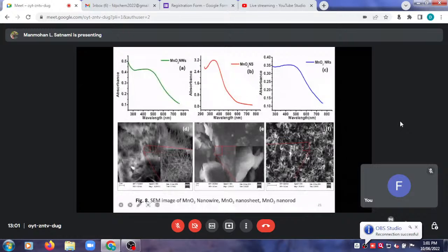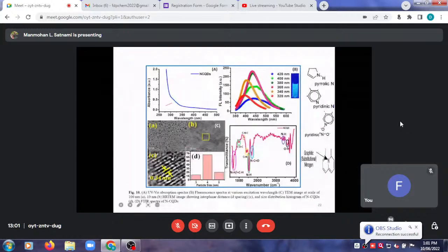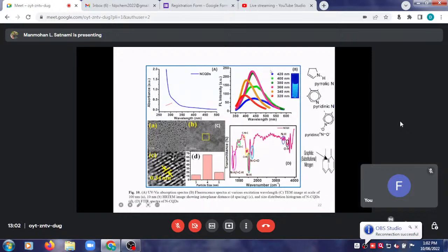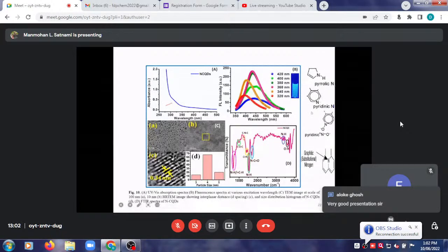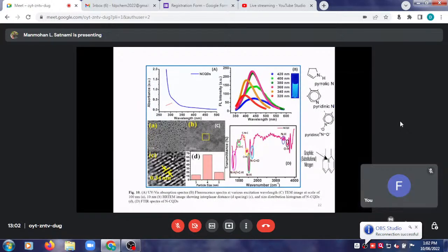Yes, we characterize carbon quantum dot through UV visible spectra. See, this is a shoulder in the UV visible spectra of carbon quantum dot, which shows the pi to pi antibonding transition. This is the fluorescence spectra of carbon quantum dot at different excitation wavelengths. You can see by changing the wavelength of excitation, the fluorescence spectra shows a red shift. This is because of the presence of different kinds of groups on the surface of carbon quantum dot. It could be pyrrolic nitrogen, pyridinic, pyridine oxide, or graphitic nitrogen. I will discuss this later.